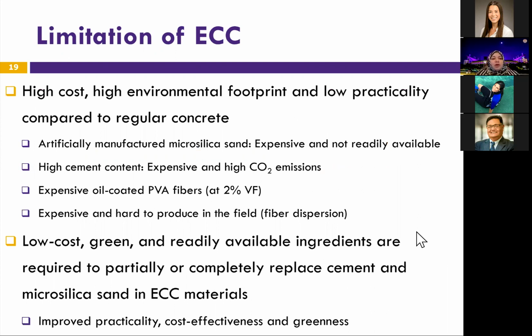Okay, so if ECC is so good, why is it currently not being used? It's because ECC has limitations. It's very expensive, and that's one of its most major limitations. It also has a high environmental footprint because it uses a lot of cement. And it's not practical compared to regular concrete, in that we have to put a lot of fibers, and they are specific fibers, oil-coated PVA fibers, according to Victor Li at 2% volume fraction. So that much fiber needs special mixing requirements for good dispersion. So not everybody can install it properly on site.